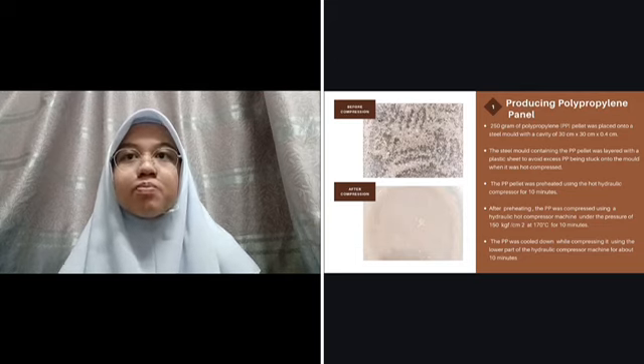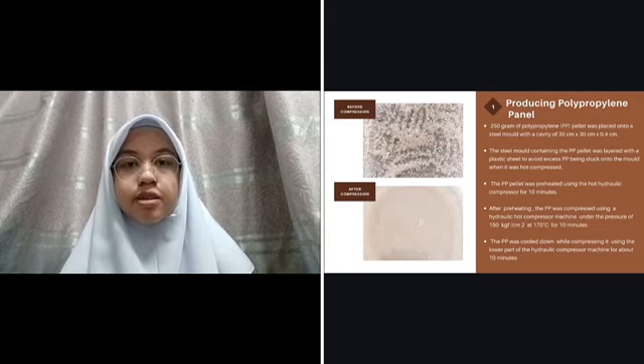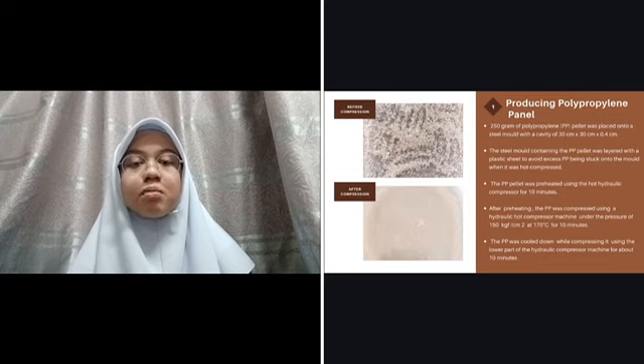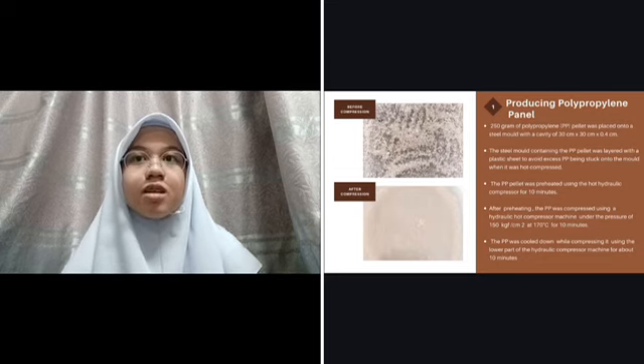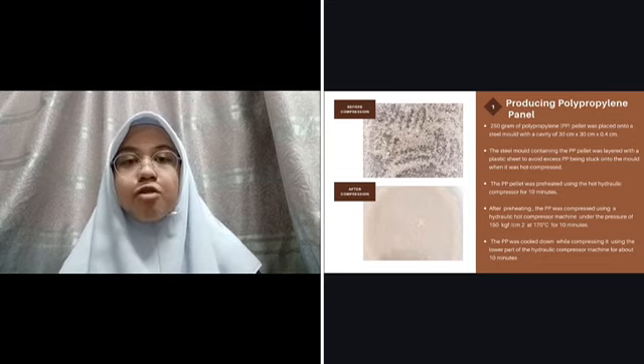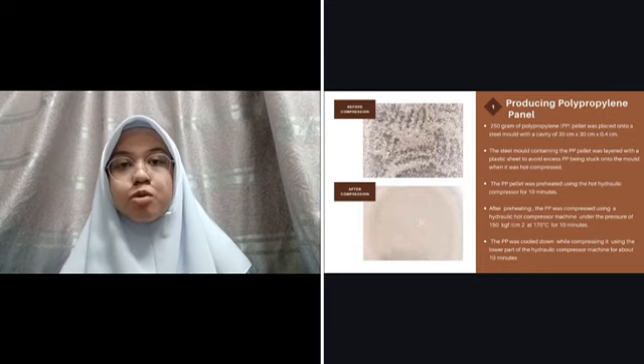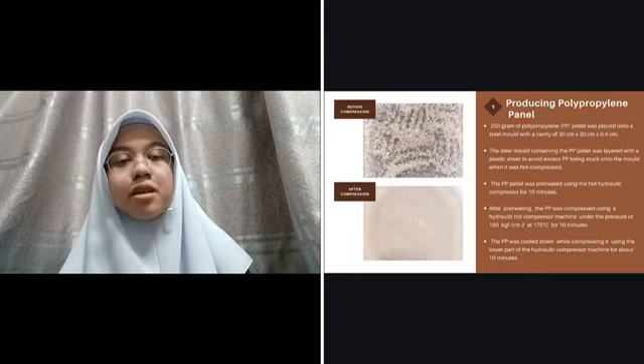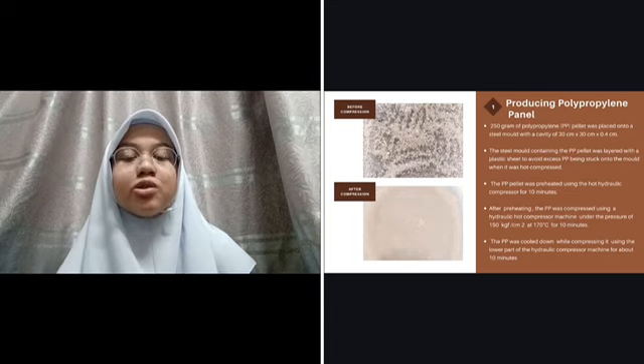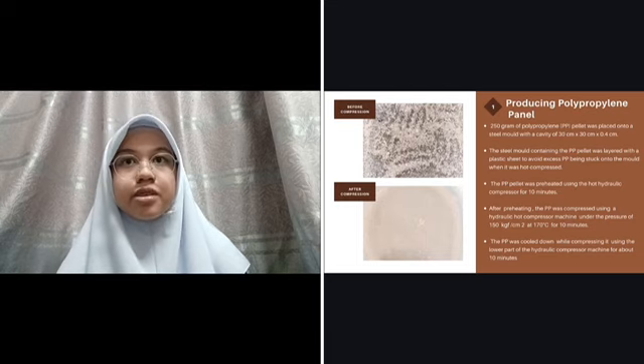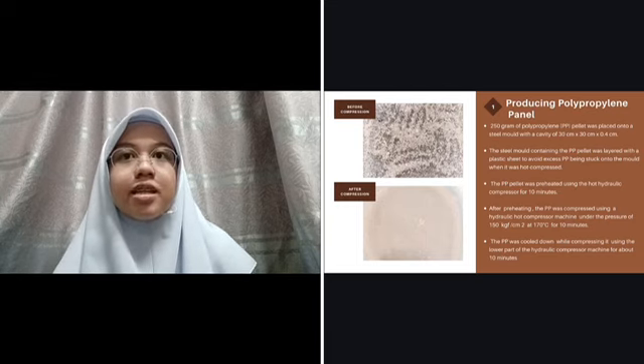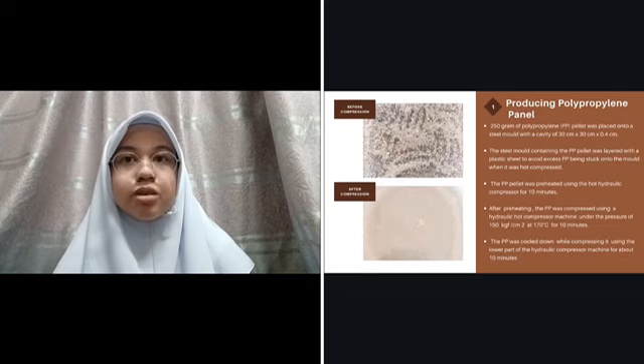The first step was to produce the polypropylene panel. For this step, we used the hot hydraulic compressor machine from Universiti Teknikal Malaysia Melaka. And we used 250 grams of polypropylene pellet to produce a polypropylene panel. The polypropylene pellet was placed into a steel mold with a cavity of 30 cm times 30 cm times 0.4 cm. And then we preheated it using the hot hydraulic compressor for 10 minutes.